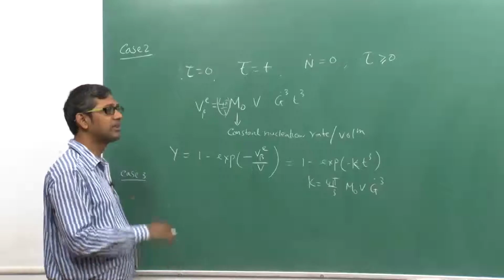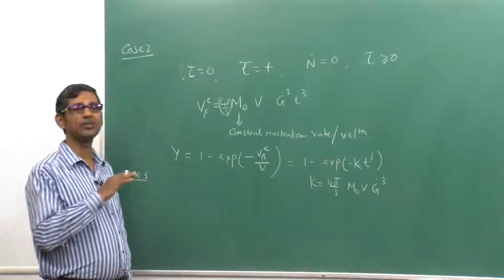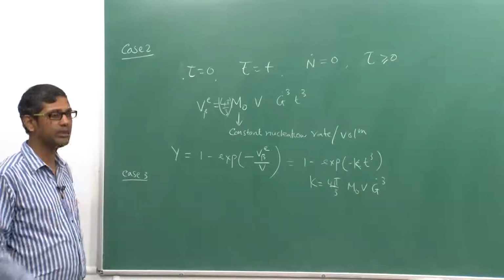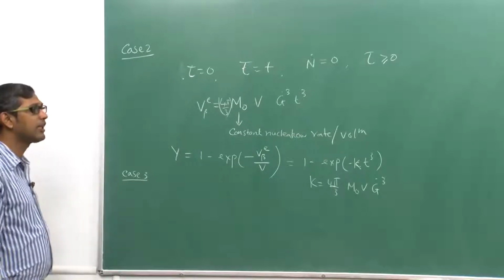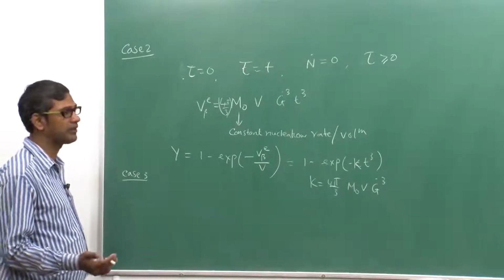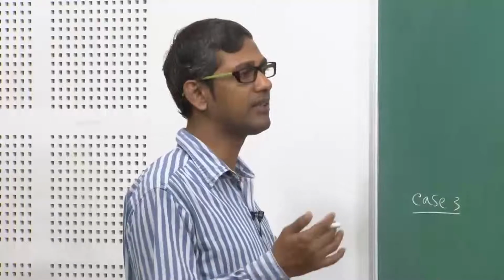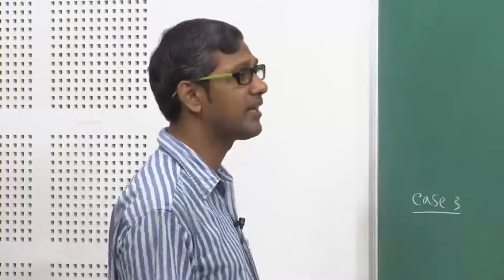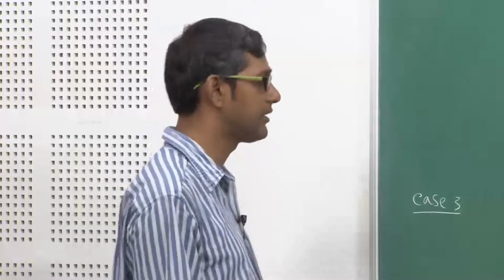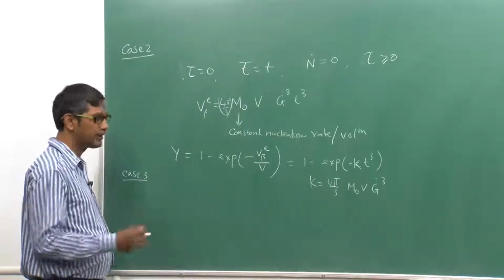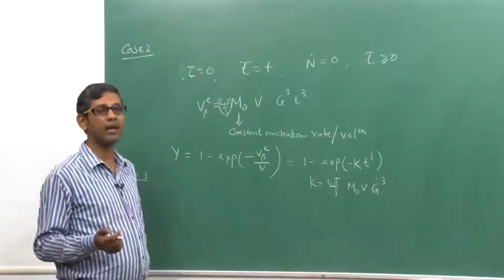In those cases nucleation will also happen randomly along the grain boundaries. So, once the nucleation happens along all the grain boundaries and it is exhausted, suppose all the grain boundary areas are filled with these nuclei, there is no further nucleation possible along the grain boundaries. So, the only possible chance is then having a nucleation inside the grain, and that is very unlikely because of the energetics of the system, which we have discussed many times in the earlier lectures. So, in these cases what will happen? When the grain boundary nucleation is exhausted, then growth will happen only.